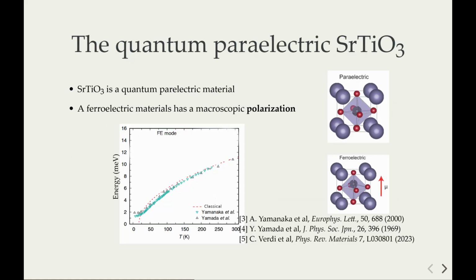And now the system I promised you at the beginning is strontium titanate. This system, as introduced also yesterday, is very interesting because it's a quantum paraelectric material. By quantum paraelectric, this means that if we look at these materials from a harmonic point of view, this would be a ferroelectric material. So harmonic theory predicts strontium titanate to be a ferroelectric. And if you look experimentally at the